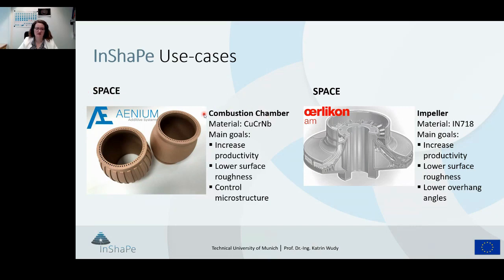And they try to manufacture components of a combustion chamber with a specific copper alloy. And the aim for this use case is to increase the productivity and to lower the surface roughness, to have a better flow behavior, and additionally to control the microstructure, because for copper applications, the control of the microstructure is always important to get a higher conductivity, for example.